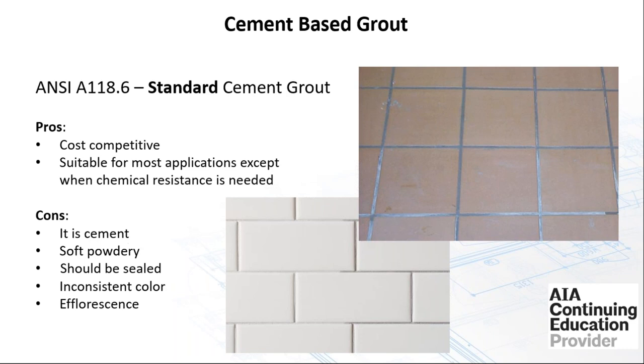So again, minimal water. I'm going to talk about this a little bit later, but water is not its friend. Cementitious products, specifically standard Portland cement grout, water is not its friend. We'll talk about epoxy a little bit later, and that is completely the opposite. I'm sure we've all seen this. And the other thing you can get is an efflorescence. Efflorescence is when water is getting into the grout or behind the grout and pulling the minerals from the Portland cement-based grout to the surface, and you have that white film going down.